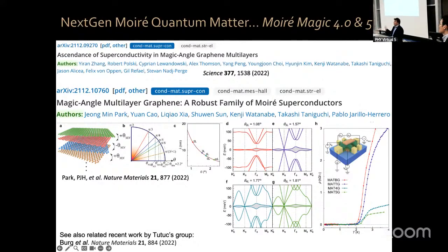However, the symmetry we see is very strong, so it's not very clear if that is enough to give you the degree of asymmetry observed. As you mentioned, in the cuprates it's very asymmetric, and yes, you're using different families, but it's not clear to the cuprates community that that's the origin of the difference. Some people think the behavior of holes is very different from the behavior of electrons. So we do not yet have a good theory for why there's this degree of asymmetry.